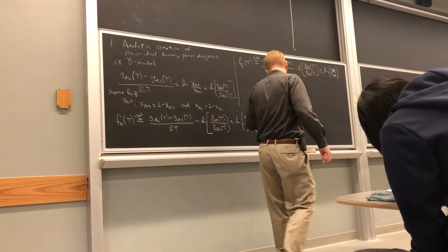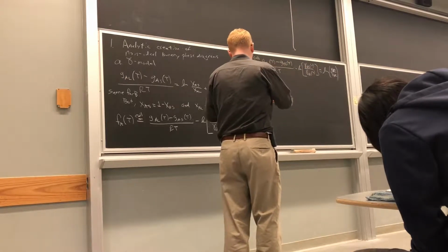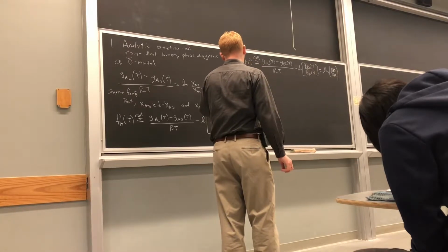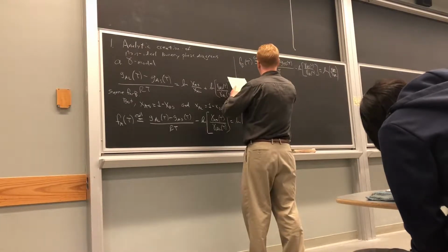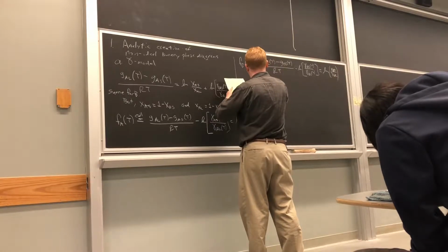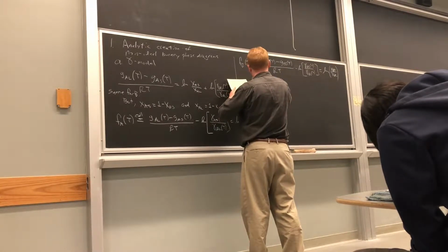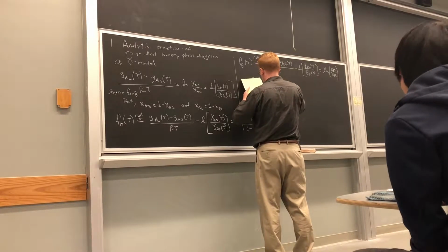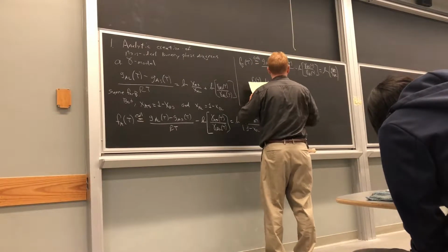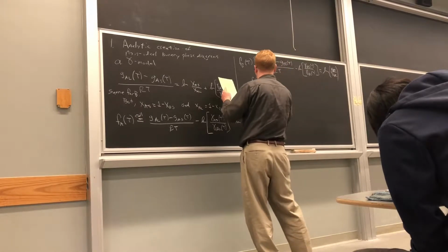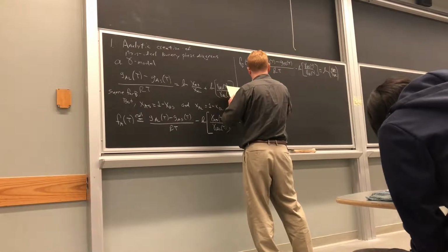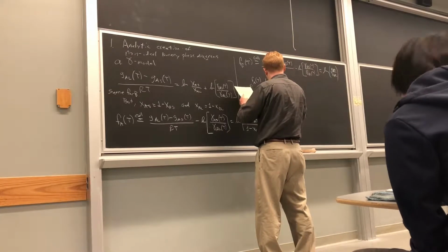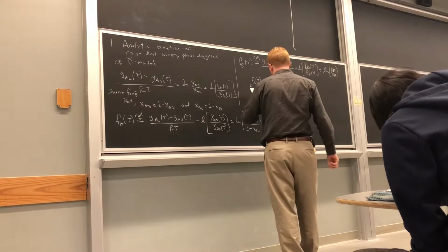All right. So then what you can do is you can say that e to the F_A as a function of T is 1 minus X_BS over 1 minus X_BL. And you can say that e to the F_B as a function of T is equal to X_BS over X_BL.